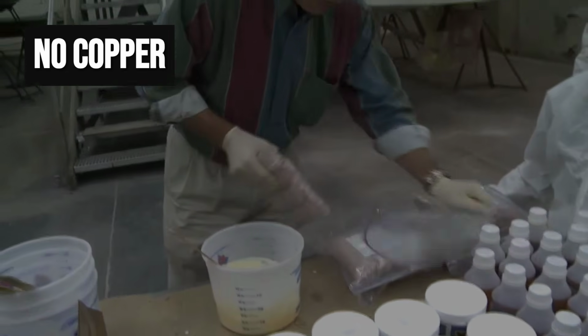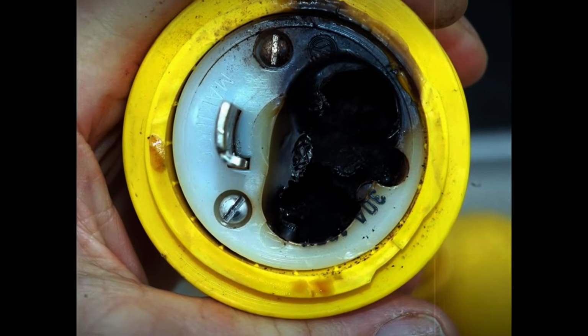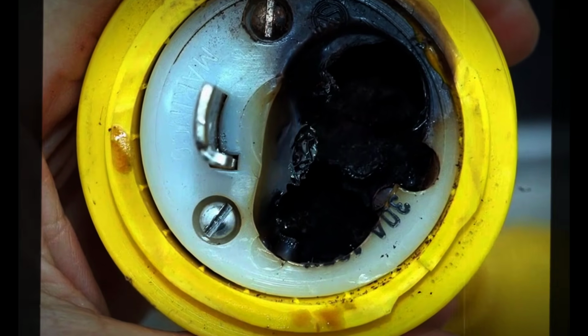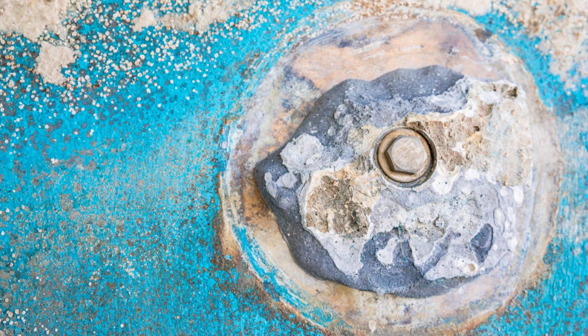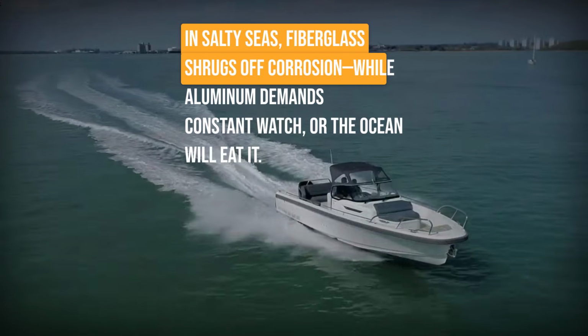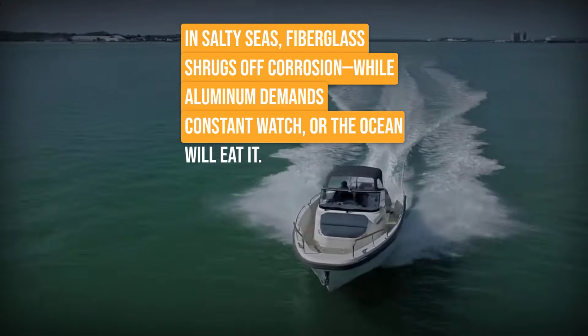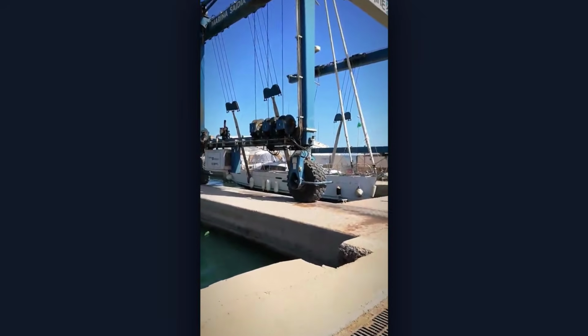Copper-based anti-fouling paint cannot be used on aluminum hulls, because the copper in the paint creates exactly the galvanic situation you are trying to prevent. And if the boat is moored in a marina with stray direct current from faulty wiring on neighboring boats or the dock's shore power system, that current can cause serious structural pitting in a single season regardless of how well the anodes are maintained. Fiberglass wins the saltwater durability comparison, but only if the hull was built with vinylester resin, which resists osmotic blistering at a significantly higher rate than polyester, and only if it is hauled annually and the bottom is maintained properly.